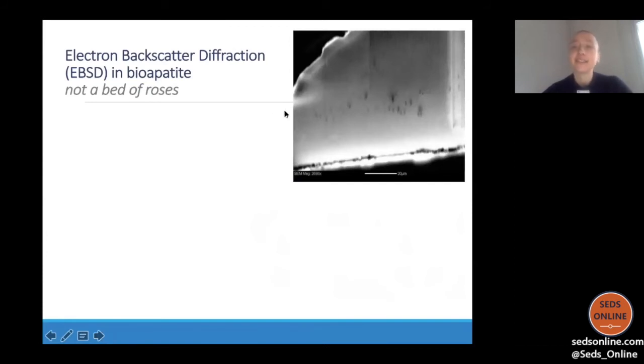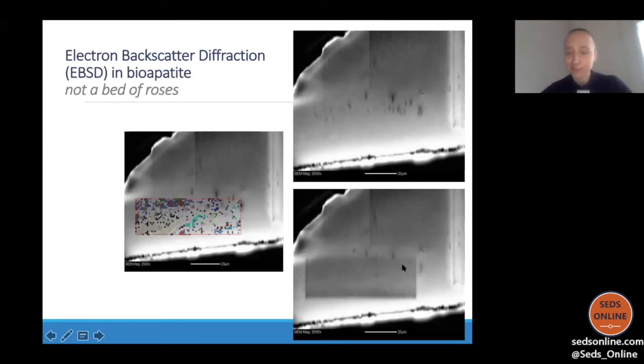So we tried, and this is a very early try. There's a lot of charging in this SEM image, but the worst thing here is that to do EBSD, you run an electron beam on your mineral in a series of lines. And in this conodont sample, we see immediately how we basically vaporized the material after one single run. So every time you measure once, your material is gone. This is like a Schrodinger's conodont. And the map that we were getting, I wouldn't say it's completely random, but it's almost empty. The indexing rate, the proportion of pixels that give any signal, was below 50%. For any carbonate specialist, that would be completely unacceptable, because when you work with carbonates, we're talking about indexing rates of probably around 95%, tending towards 100%. So we were like, this is terrible.